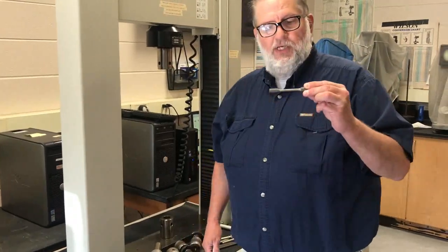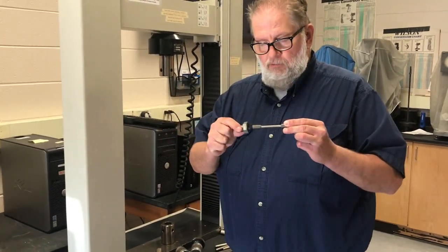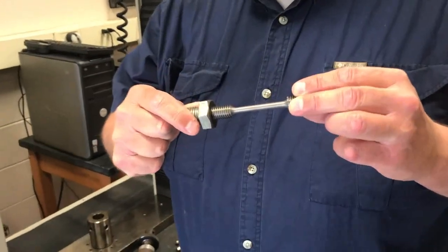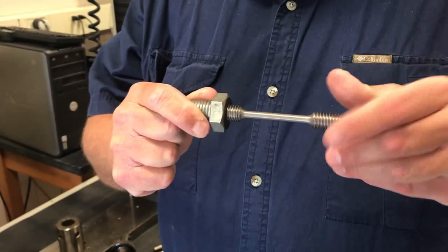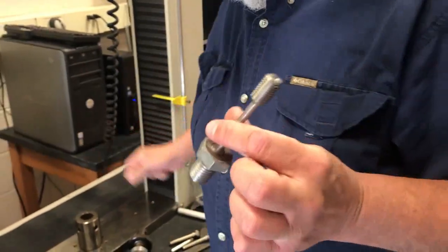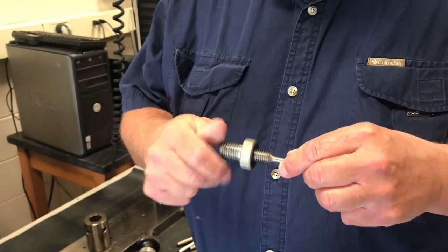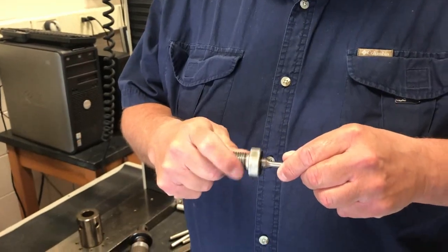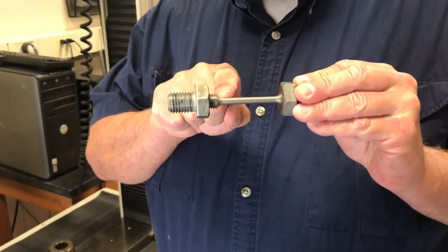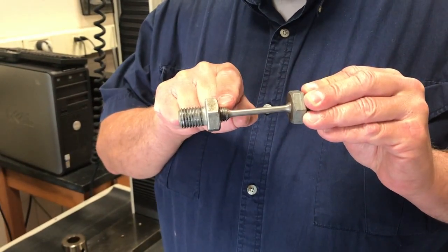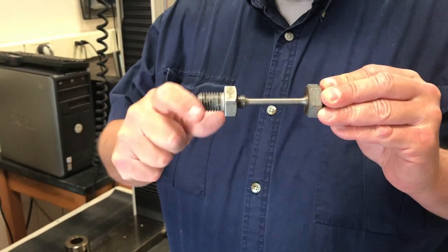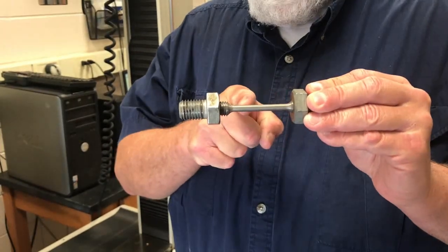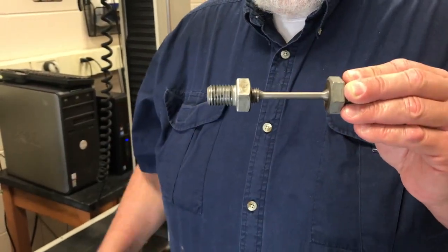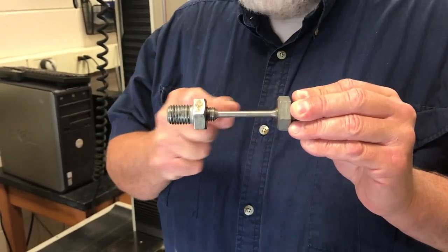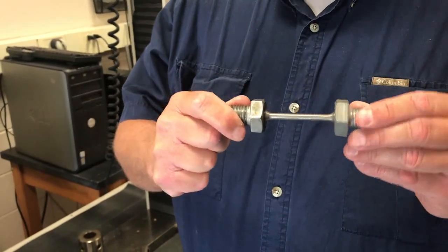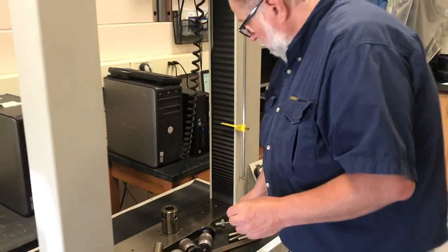Now I'll show you how to attach the tensile test sample to the machine. Take your conversion fitting, either one, thread the sample into the interior threads in the head of the conversion fitting. Thread it in all the way, hand tight, and then thread the other end of the sample into the other conversion fitting. Now, one thing I forgot to mention, another important feature of the tensile test sample is that you have a smooth transition or fillet between the test region and the threaded portion. Again, that's to eliminate stress concentrations or singularities that can cause the sample to fail in application. You want the sample to fail in the center, far removed from the grips, to make sure that we don't have a stress concentration. So that fillet, or that smooth transition, is very important. So thread both conversion fittings onto the sample, and now set that down for a second.